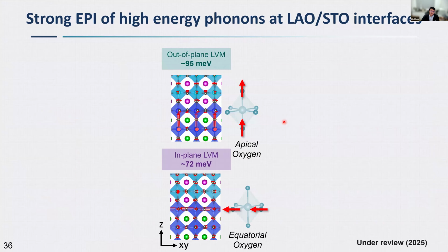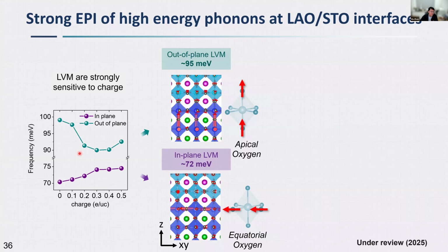And the theory also shows that if we're looking at the vibrational modes for this out-of-plane localized vibrational mode at about 95 milli-electron-volt, it's mostly contributed by the apical oxygen in those octahedra. And the in-plane vibrational mode is mostly contributed by the equatorial oxygen in the TiO layers. And also we see that both modes are very sensitive to charge doping, and as you increase the charge concentration in the calculation, you can see how it shifts in energy, very consistent with the experimental observations.